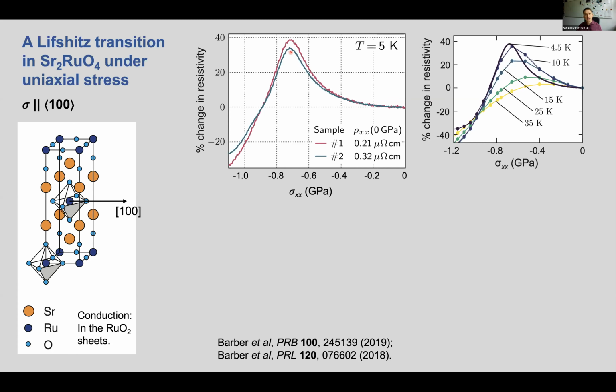I think even more striking than that is when we go beyond this Lifshitz transition, we see this very strong decrease in the resistivity to well below values seen at 0 stress. So we know well that strontium ruthenate is an unconventional metal at 0 stress, that it has strong electronic correlations. I think that what we're seeing is that these correlations are then strengthened as we reach the Van Hove singularity, but then are very rapidly suppressed as we go beyond it, and strontium ruthenate seems to become a much more conventional metal at very high stresses. That is a general theme along which we're still working.